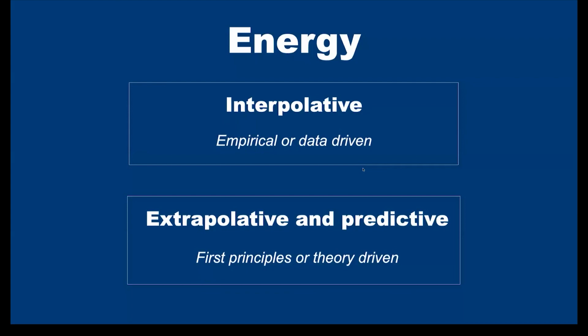Now, traditionally, before I started working in crystal structure prediction, the assumption had been that the exploration of these complex energy landscapes was going to be so computationally expensive that you couldn't dream of using first principles methods to evaluate them. So pretty much, with one or two exceptions, structure prediction at that point involved using empirical potentials. This is what I would call an interpolative method, an empirical potential based on observations that we've seen before. As you'll see later on, these interpolative or empirical methods have come back in the context of machine learning or data-driven techniques, and I'm going to emphasize that towards the end of the talk.